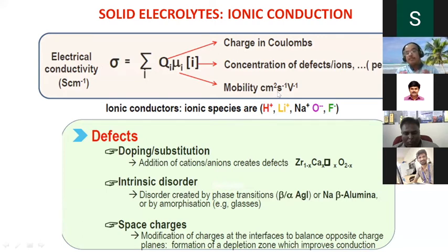So addition of cations creates defects. So intrinsic disorder created by phase transition, that's what I call beta to alpha phase of silver iodide, or sodium beta alumina amorphization. So this is space charge. Modification of charge at interface to balance opposite charge planes, that's what I call formation of a depletion zone, which improves conduction. Which means that the defects really help. So if the concentration of defects is larger, then every possibility that you can improve the conductivity.